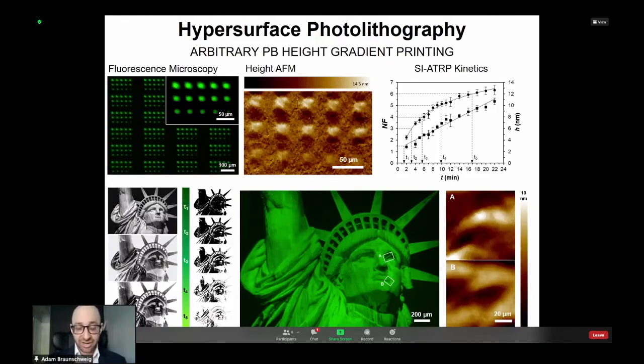Now, again, this is showing our accelerated optimization of surface reactions. What we wanted to do was create patterns where we could control the brush height very precisely at each position. So the first thing we did here was we printed polymers of different heights of a vinylic monomer with a small amount of fluorescein methacrylate doped in. Then what we did was we took the AFM and we can correlate fluorescence and height. So once we have this correlation, we don't have to do AFM every time, but we could use the fluorescence to determine the height of the polymers.